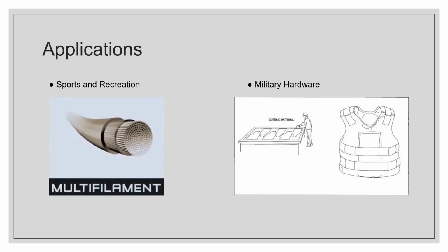For these applications, Kevlar is packed into a multi-filament string where several filaments of Kevlar are glued and strung together in a similar process mentioned previously. The multi-filament strings are then coated in silicone to protect the string and also to prevent any fraying during play. The advantage of multi-filament strings is that manufacturers can vary the type of filament inside the string in order to achieve the desired effect.